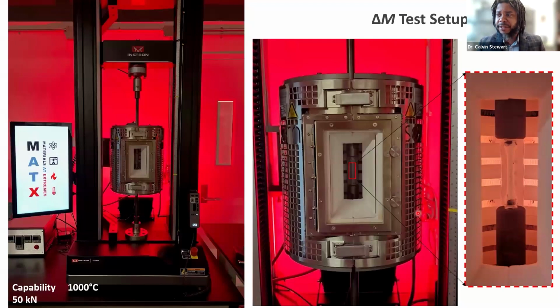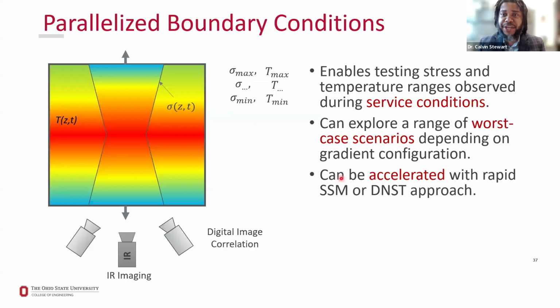So we've built another test setup we call Delta M that gives us a full field view of our sample from tip to tail, that also has very fine control on temperature, plus or minus 1 degree Celsius, with this big window on it, right? So this setup allows us to test up to 1,000 degrees Celsius, pretty hot, not 1,400 or 1,800, but still pretty hot, with a load capacity of 50 kilonewtons. And so we can then configure this and be able to measure the strain on the surface and be able to determine in those regions, in those zones, which composition will survive.